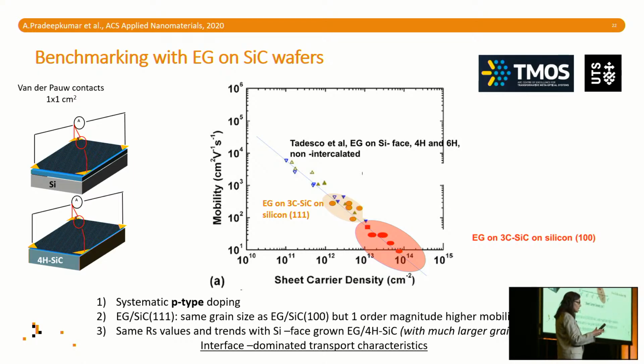So we're really looking at large scale as much as possible. These are graphene samples grown on our 111 face, and these are graphene samples grown on the 100 face of silicon carbide on silicon. And these are numbers that come from literature from collaborators, taken on epitaxial graphene on silicon carbide wafers, so the hexagonal ones with large grain sizes. And you can see that we sit exactly on the same line, pretty much.